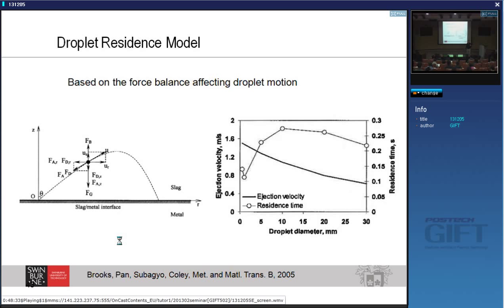The way oxygen steelmaking works is that when you blow at the start, the droplets have so much gas associated with them that they float. And because they float, they spend more time inside the vessel. At the end of the blow, they are dense. They don't have much gas. So they just sink. So the kinetics slow down. So let's go on to what that means.